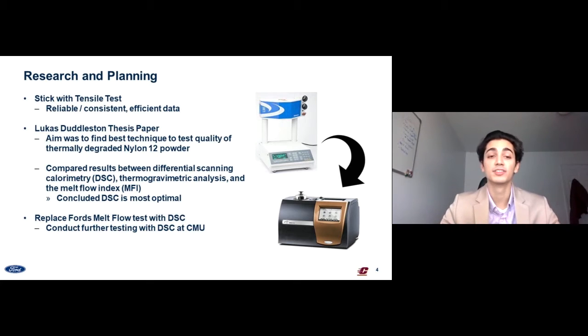First thing first, like we mentioned, Ford already has implemented 2 tests, the tensile test and the melt flow test. What we've seen from the tensile test is that it's a really reliable and consistent test. It provides efficient data consistently for us, and there's nothing wrong with it, so there's no need to replace it. The tensile test is a great test in telling us what the strength of the material is, the dog bones, and to see the quality of the powder in one way.